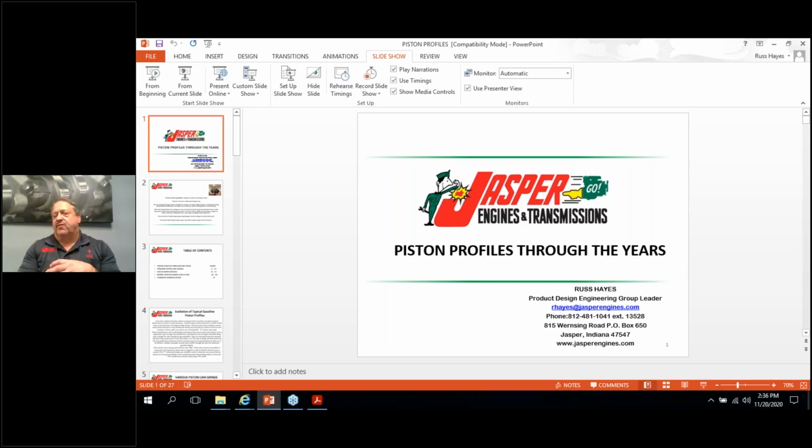My rule of thumb is that if I have a HyperEutectic piston that takes more than 2.5 thousandths clearance, I'm going to induce a rock. I would say that applies to a 1.5 millimeter top ring. If I had a 1.2, I would like to see a little bit less than that, probably 2.2 thousandths max. And just to let you know how critical profiles are, we're able to run our forgings, which are 4032 alloy, in our HyperEutectic with the same clearances. So we're running forgings at 1 thousandth clearance minimum, and then we have a skirt coating on top of that.